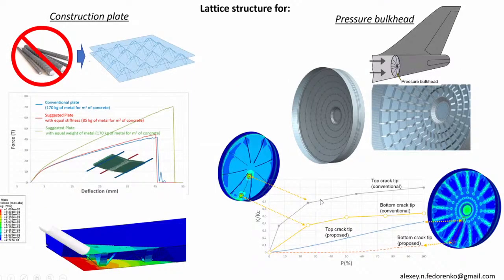In this work, we consider two cases for industrial application of lattice structures. So this is not 3D printed. We can make it using stamping and welding. So the first one, the idea is to remove reinforcement bars and to use such a lattice structure. So it is filled by concrete between outer sheets. And using finite element analysis, we found that we can increase the stiffness and the strength of construction plate with the same mass of metal parts.